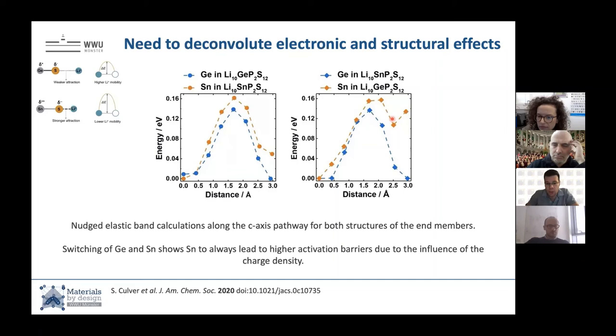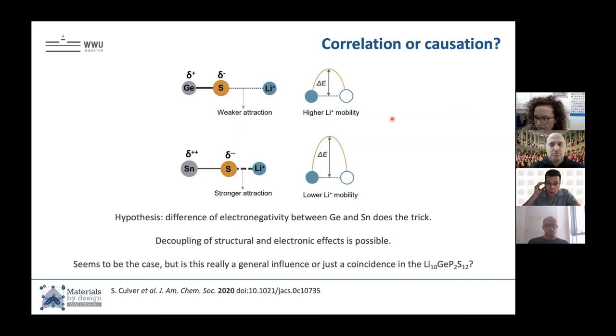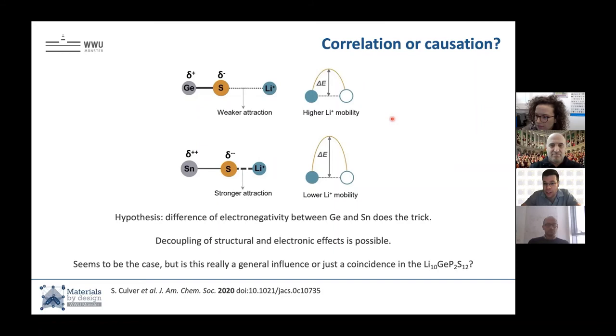We at least believe the inductive effect is real in LGPS. This type of effect has been observed in cathode active materials since the 1980s, so it's not entirely surprising. But it's interesting to see it holds up in solid ionic conductors. The question remains: is this a general influence or specific to this tunnel-dominated structure? Many people, ourselves included, sometimes invoke the inductive effect when we observe strange changes in transport we can't otherwise explain — the field has work to do over the next few years to determine when this explanation is truly valid.